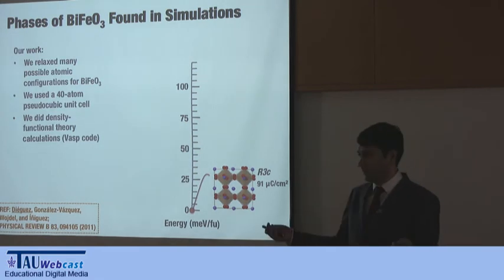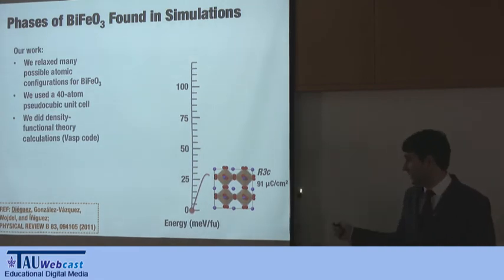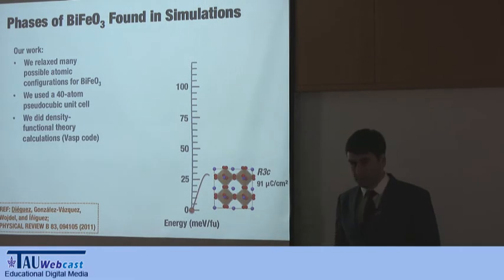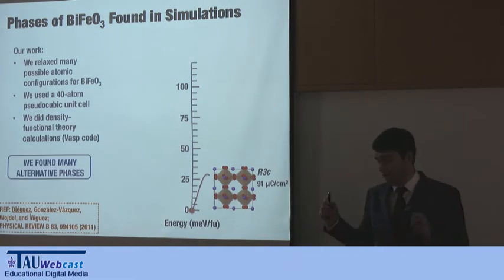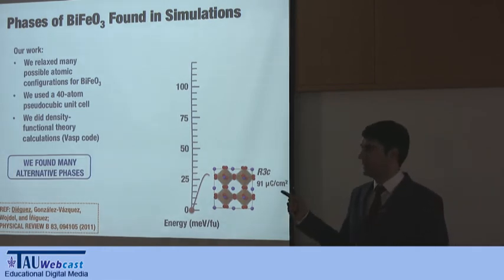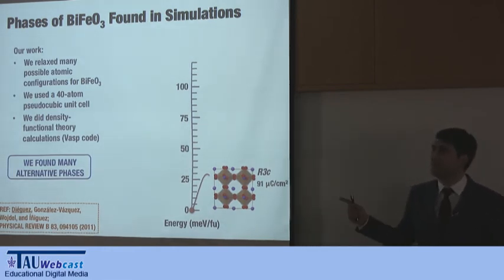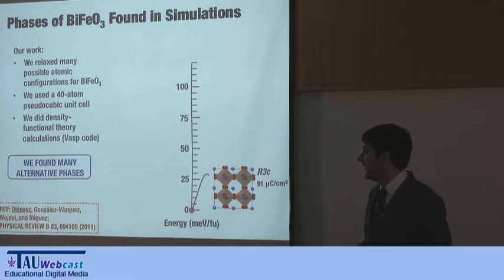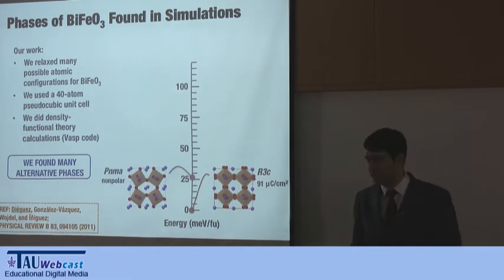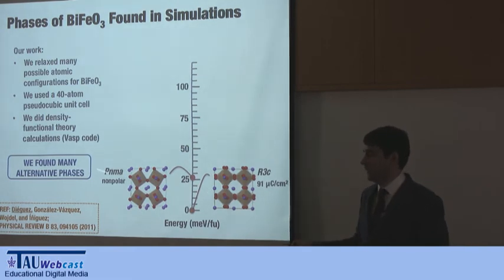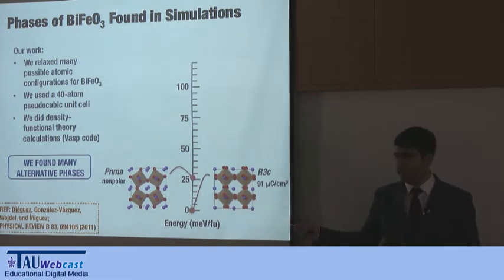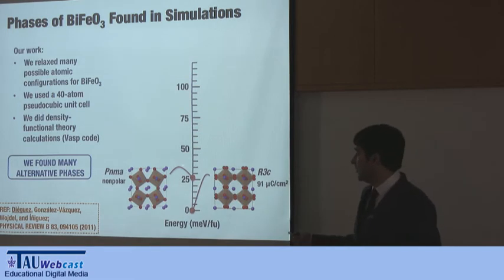So most of the trials will end up in the ground state, which is what I said before. But for the case of bismuth ferrite, and this is again not usual for perovskites, there is a huge lot of minima that appear, of the order of tens. So there are many different phases that it can take. One is this one that is nonpolar, and where the octahedral rotation follow a different pattern. So this comes from our simulations.